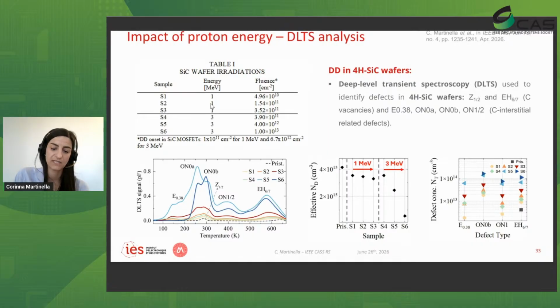The second one was irradiated at the onset, and the third well within the fluence where we are observing displacement damage. So we had different fluences among them. And then we performed deep level transient spectroscopy to identify the defects that were created in the material. This is a spectra from the DLTS signal as a function of temperature, where we can see with respect to the pristine here in gray that there is the formation of different peaks depending on the wafer and on the specific irradiation conditions.